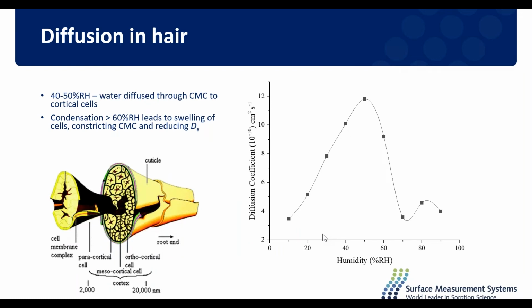So to understand the changes in these diffusion coefficients, first we need to understand what it means in hair. And so these are the diffusion coefficients for untreated hair. Now, diffusion in hair is governed by two stages. First being water diffusing through the CMC to the cortical cells. And this occurs until about 40 to 50% relative humidity, where we see this maxima. After this point, water begins to condense in the cortical cells, which leads to a swelling of the cells, which constricts the CMC, which is around the cells, and then that is followed by a reduction in our diffusion coefficient.